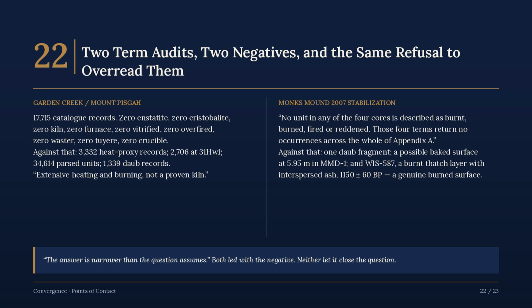11 months later, the Garden Creek catalog audit runs the identical instrument across 17,715 records and returns the identical shape of answer. 0 enstatite. 0 cristobalite. 0 kiln, furnace, vitrified, overfired, waster, tuyere, crucible. And against that negative, 3,332 heat-proxy records, 2,706 of them at Garden Creek Mound 1, 34,614 parsed units, and 1,339 daub records. The verdict: extensive heating and burning, not a proven kiln.